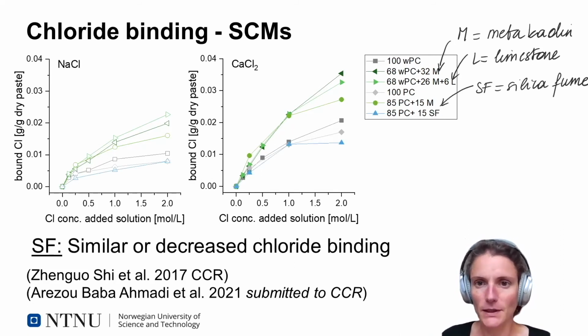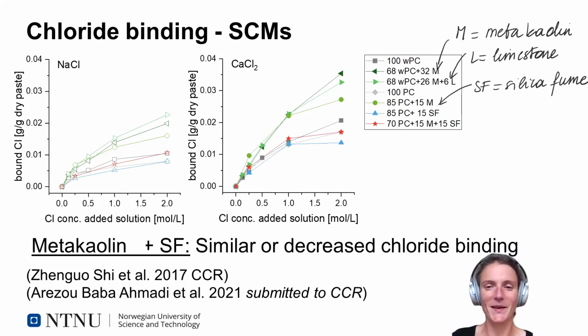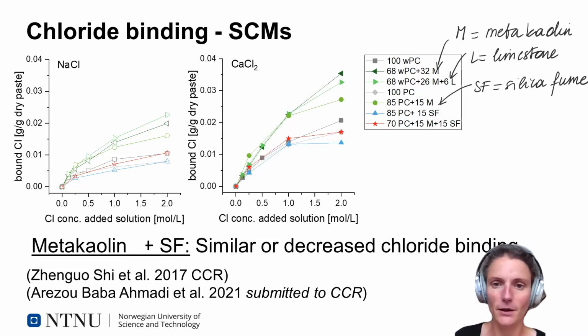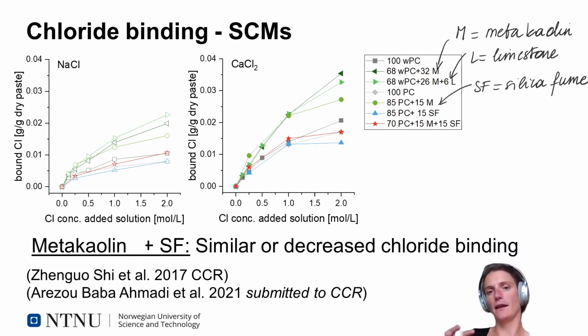When we add silica fume to the system, for example, 15% silica fume, we see a similar or decreased chloride binding. It's also been observed before. And then interestingly, Arizu, she combined metakaoline, so 15% metakaoline with 15% silica fume. And we can see that the silica fume is actually cancelling out this beneficial effect of the metakaoline on the chloride binding. Now, if you want to explain how these SCMs are affecting chloride binding, you really have to have